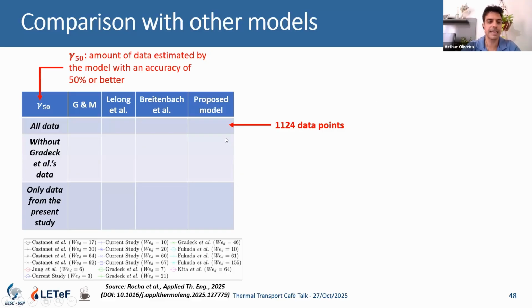We also did the analysis considering removing Gradeck and colleagues' data from the analysis, because among the more than 1,000 points, more than about 900 points came from Gradeck and colleagues' data. That's a very powerful database they have, and that's only possible because they did a transient analysis, which allows you to have a very good and very large database. So to be fair to the others, we also did this analysis removing their data and comparing with the data from our paper.